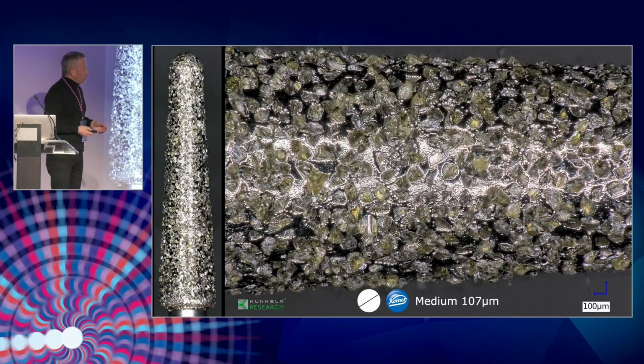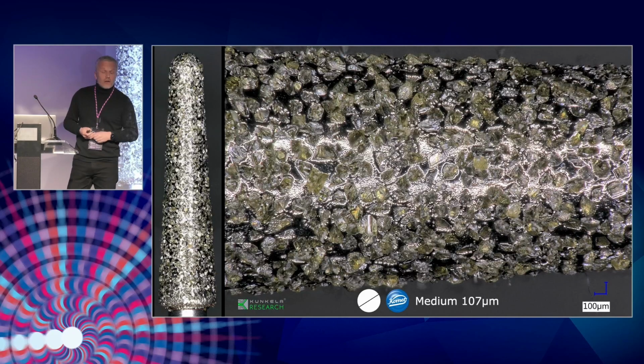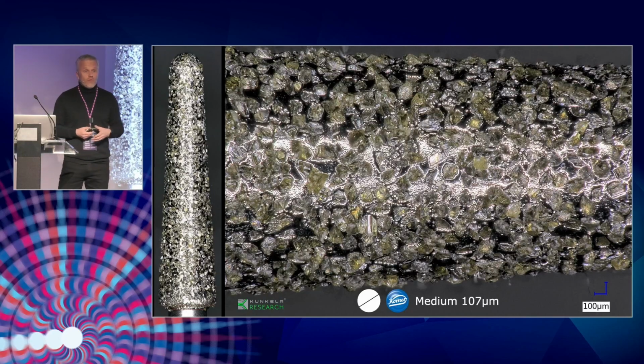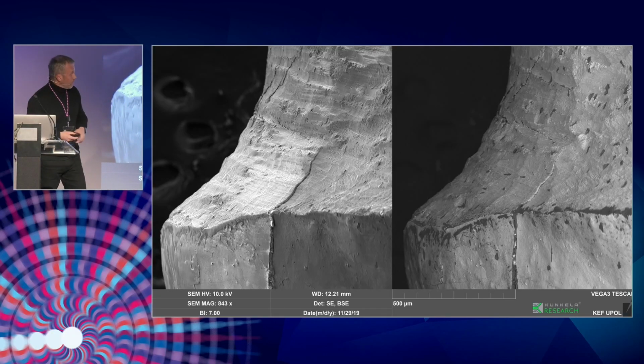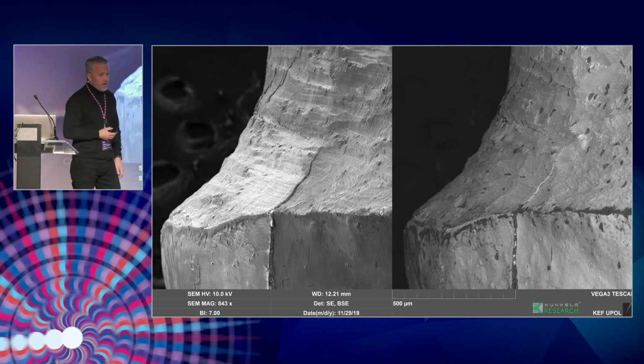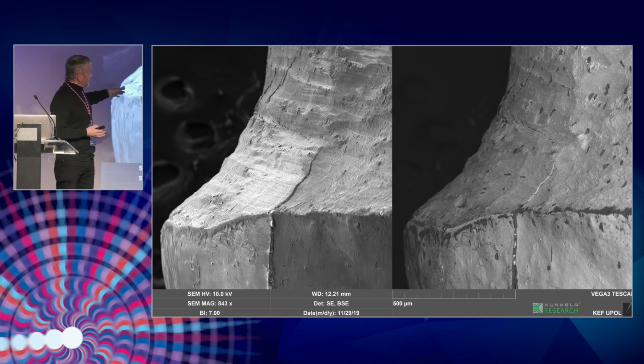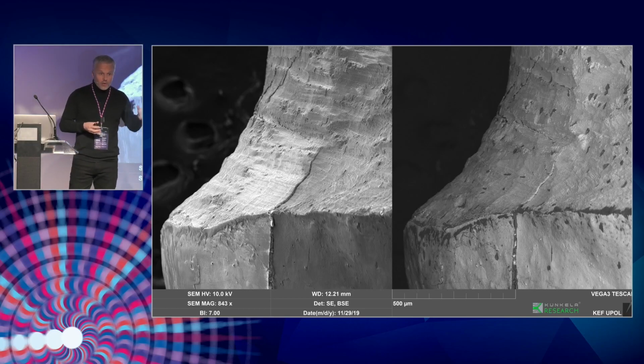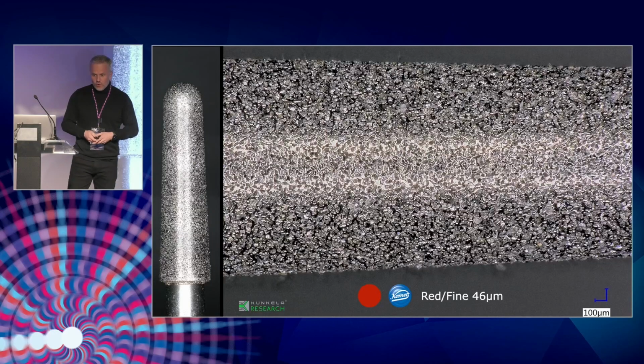This is how a preparation looks with the medium coarse instrument, where the average particle size is 100 microns. And this is how the tooth surface looks with the SEM microscope. You can see the chippings are fewer, but internal cracks are visible, which are totally invisible to the human eye. I think it's one of the things which can be responsible for post-operative sensitivity. If we are not treating the bonding surface well, for example not using dentin sealing, once the dentin is exposed, these cracks can be responsible for post-operative sensitivity.